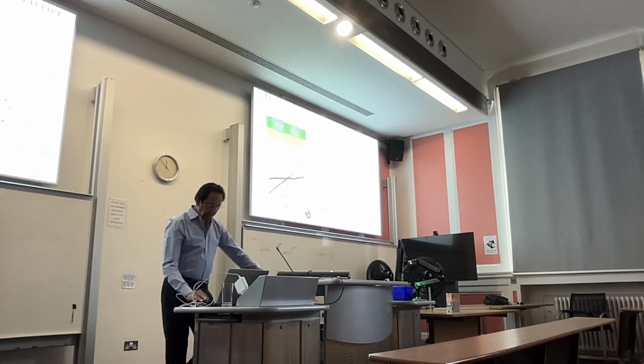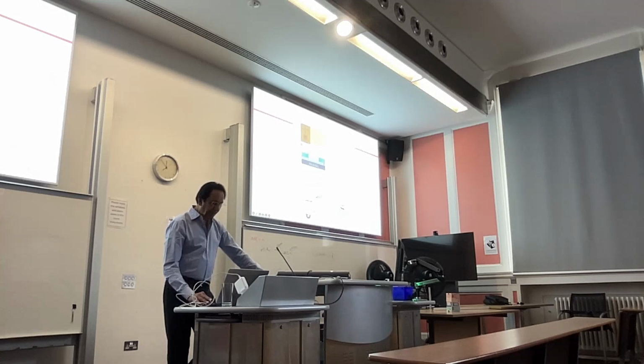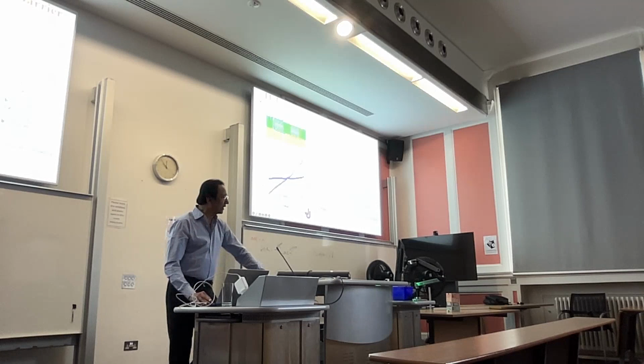So anyhow, that gives you an idea. And we started exploring how many ferroelectric layers I can insert as a barrier. Here, for example, we are able to go down in this curve. You can see the number of unit cells of the ferroelectric layer that I can put in and still get a hysteresis loop. We are down to about 2 unit cells with barium titanate, and we have now gone to bismuth ferrite, and this is actually 1 unit cell of bismuth ferrite, and you can still get a tunnel junction.